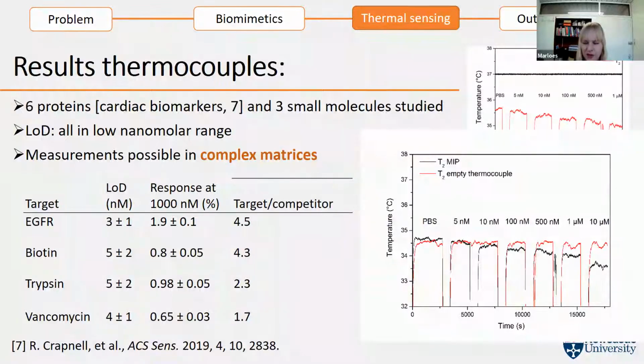So we add something to it, and you will see that the red line stays roughly the same. But when we've got really low concentrations of, for instance, proteins like biotin and trypsin, we see a drop in the temperature, which is associated with this increase in thermal resistance.